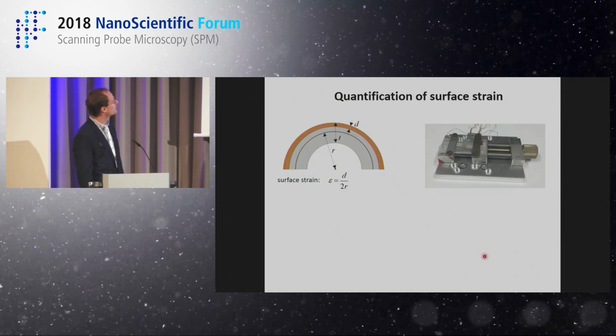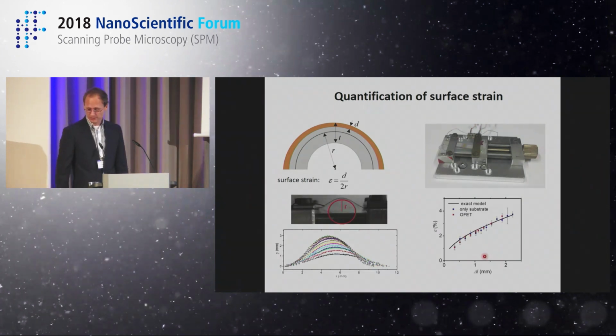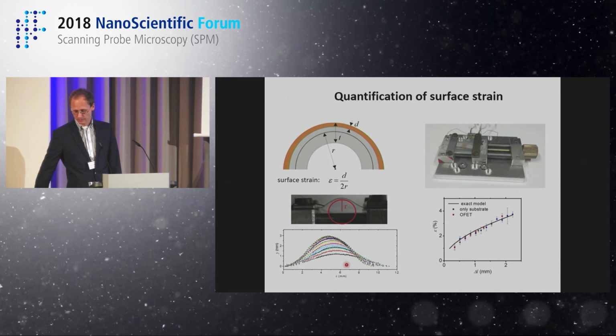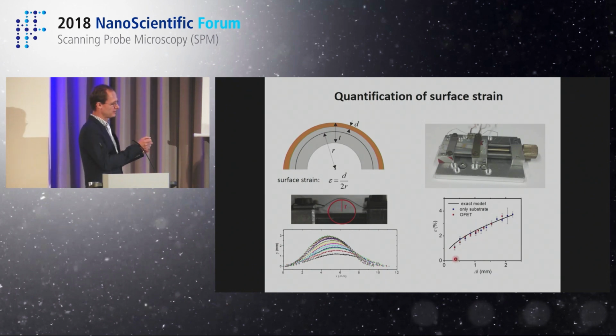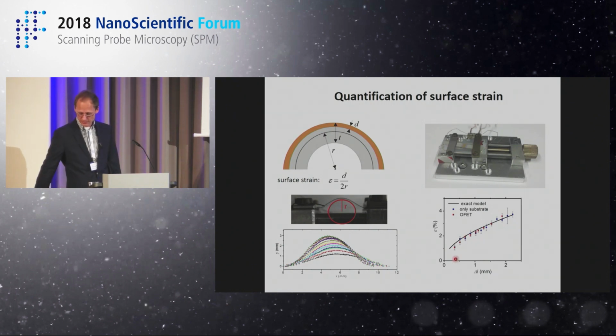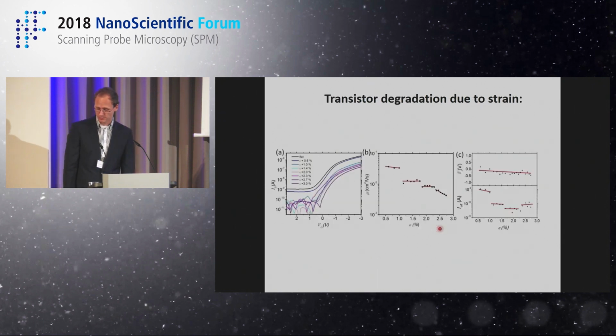Okay, how do we do the tests of strain? Basically, we deposit these transistors on a flexible surface, and then we start to bend it, and we can investigate just by contacting the transistor and measuring how it works. This is how we investigate the bending with a small camera, and then we can calculate the surface strain. You can see that it's not comparable to something that is elastic. However, if you bend it strong enough, you can get to strain values on the order of a few percent in such electronic materials, so something that is definitely not negligible.